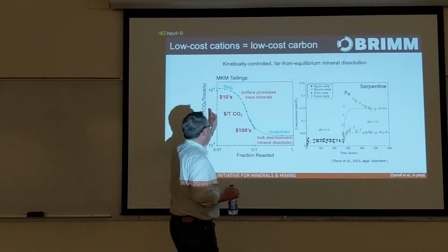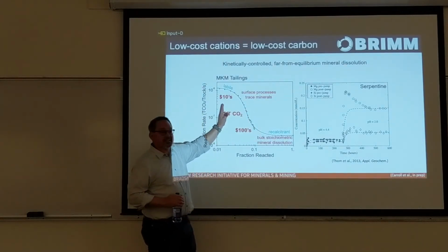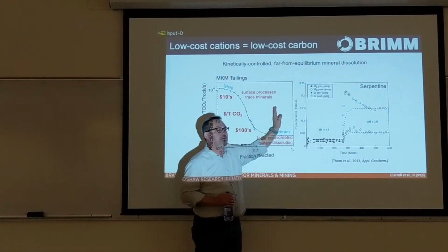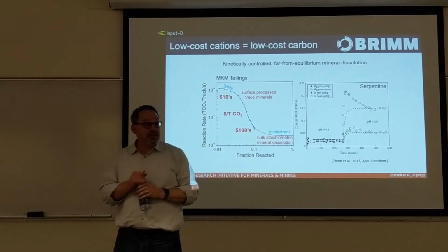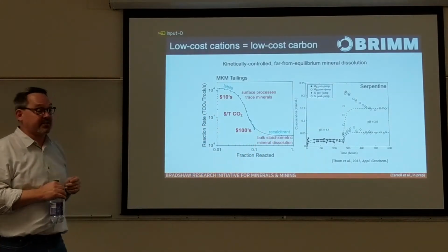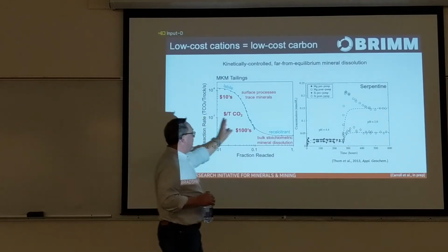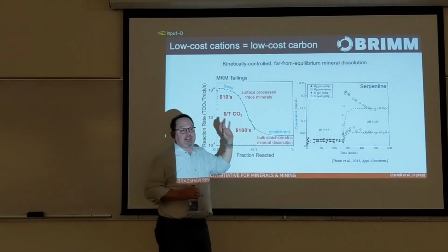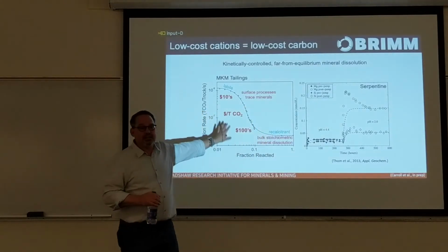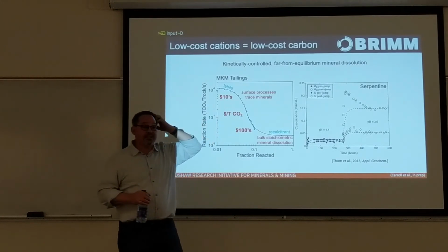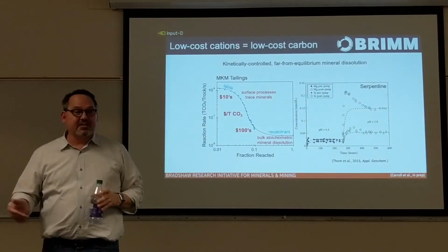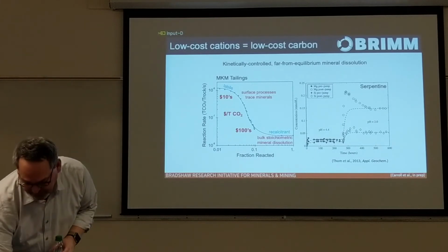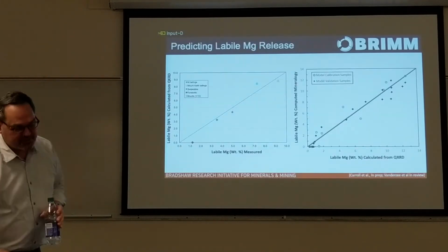So you can think of it, when we do this measurement, we find some materials have less than 1% labile magnesium. We get labile magnesium contents of 14–15% in some materials, all within a single deposit. So obviously we want to work on the material that has a high labile magnesium content, but even though this is an automated system, we can't run this experiment on thousands of samples in order to get an understanding of an individual ore body, let alone a bunch of ore bodies.